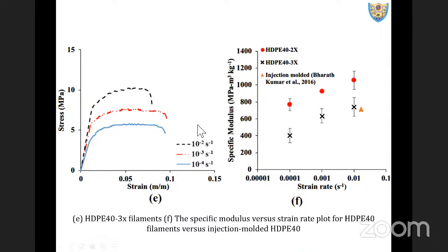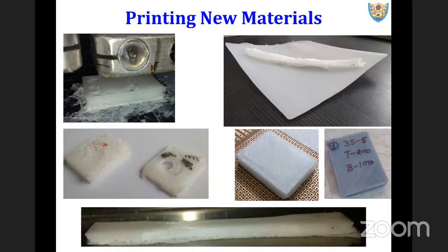And that's how it is useful if you do any mechanical test at different strain rates, which gives you additional insight into how the material behaves if the strain rate changes. And this is what we do for our development, wherein we need to look at different applications at different rates of loading. So this is an additional thing which all of us can do once we develop a new material system. Once you develop a 3D printing filament, and assure yourself based on a tensile testing of the filament as compared to the injection molded sample for the same material composition that the filaments are doing well, then definitely you should venture into 3D printing, because that gives you an assurance that the time and development efforts spent are worth it.